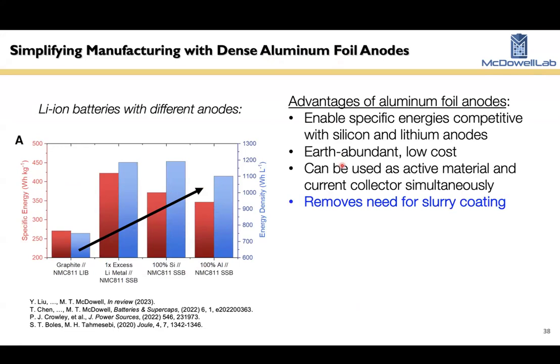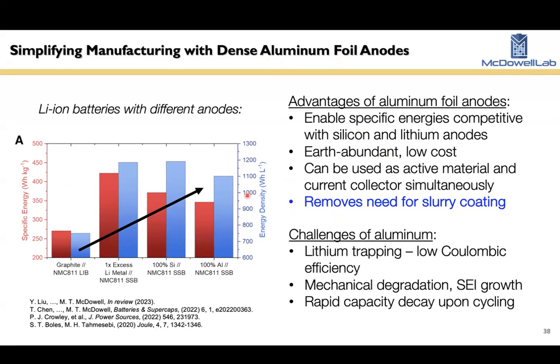But if you're using a foil directly as an anode, you get rid of all the slurry coating that you need on the anode side. The slurry coating in battery manufacturing takes about half the energy required because you have to recycle the solvent. And so getting rid of slurry coating is highly advantageous. And so if we can just use the foil, we could potentially have high energy density and remove some of the manufacturing costs. So aluminum in particular as an alloy anode was originally looked at many decades ago.